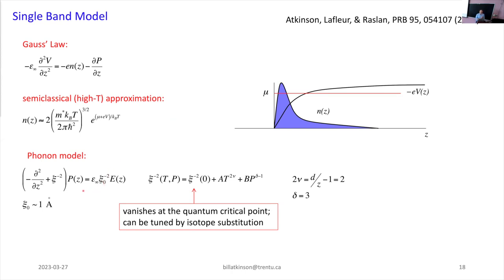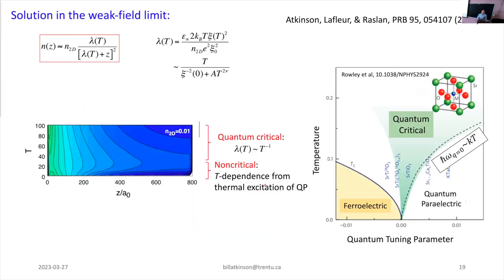And then we can take a continuum version of our phonon model. We've thrown out the nonlinear piece, so we're really thinking about weak electric fields. And the thing that controls the behavior of this phonon model is this correlation length, xi. And this correlation length is actually xi to the minus 2 that shows up here. There is a temperature correction, and then there's a correction term that comes from the polarization. Okay, so this is just a simple Landau-Ginzburg type of model for the polarization. And this can be solved analytically. This set of three equations has an analytic solution.